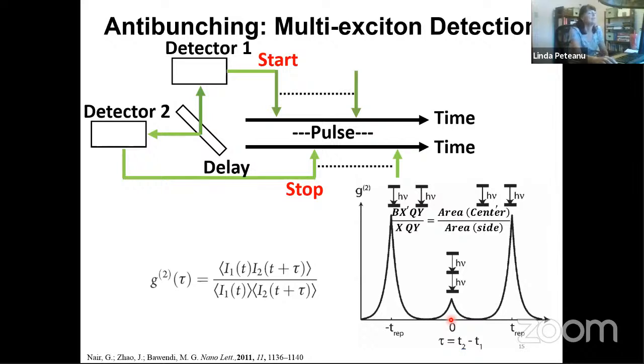So most single molecules will show what we call high contrast, or no intensity here, because they cannot emit two photons within one laser cycle. If you can emit two photons within one laser cycle, you will show intensity here. And so the ratio of the center intensity to the side wings gives an idea of the biexciton versus exciton quantum yields, because only in a biexciton state, where you have two excitations present, can you expect to see two photons come out simultaneously from the sample. So that's the basic idea of that type of measurement.